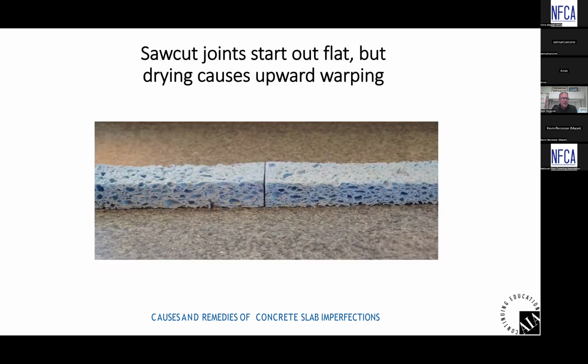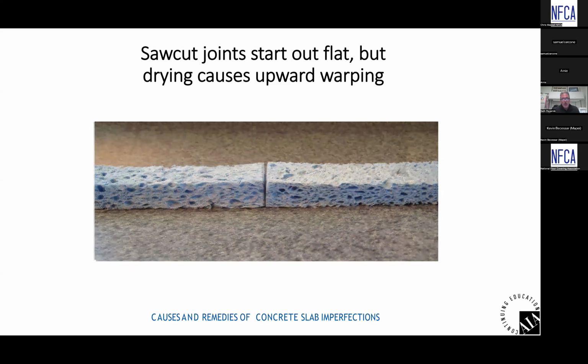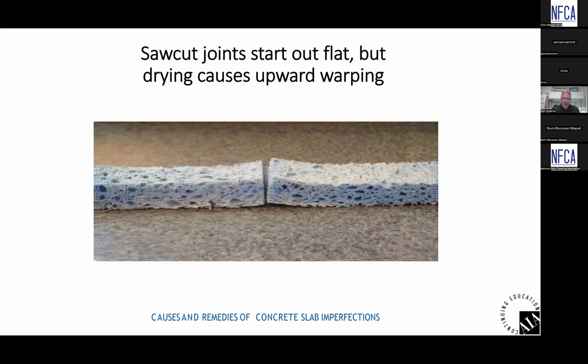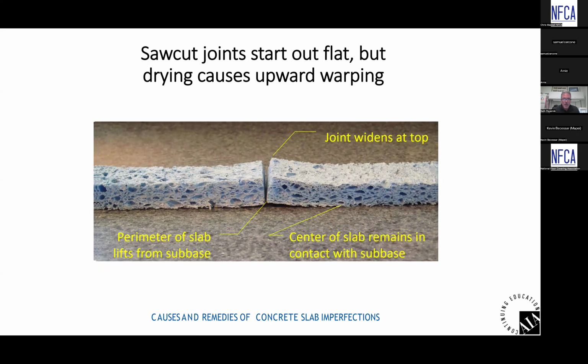To simulate two concrete slabs up against each other, we have two sponges that are totally saturated, again over a vapor retarder, which in this situation is a plastic laminate countertop. As the water in these sponges dries out, the sponges curl, and this can be compared to two concrete slabs, meaning the center of the concrete slabs or the center of the sponges are in contact with the subbase and the vapor retarder underneath the concrete, but the edges have curled up off the subbase and off the vapor retarder. And if you look at the top joint of the concrete, or the sponges in my photography here, you can see that it's wider at the top due to the curl.